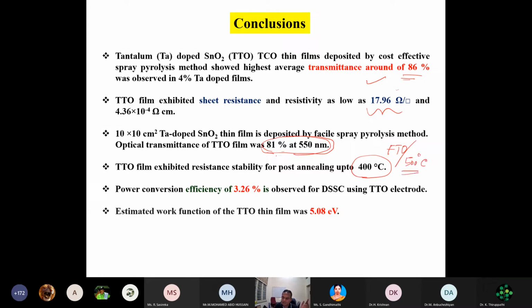But because of this only, you are having a higher efficiency there, because the layers will be formed properly when you make a device. Whereas the annealing temperature is lesser for this particular sample. So we have to see how we can improve this temperature stability so that it can be on par with commercially available FTO. And DSSC is showing 3.26% efficiency, and the surface work function is 5.08 electron volt.